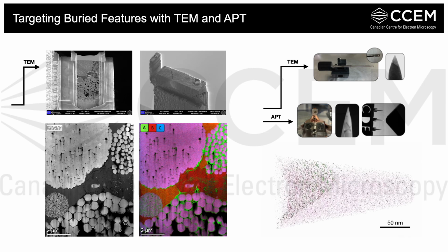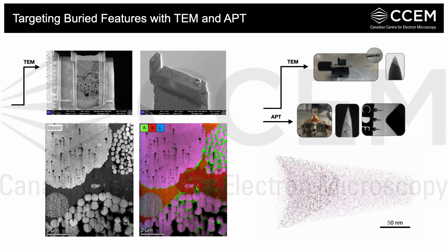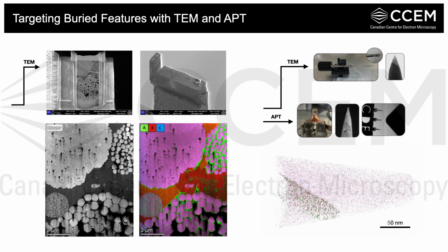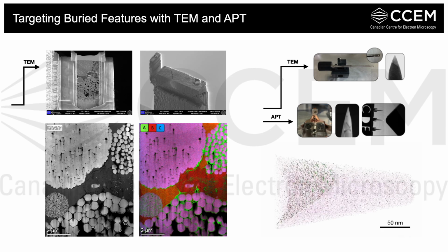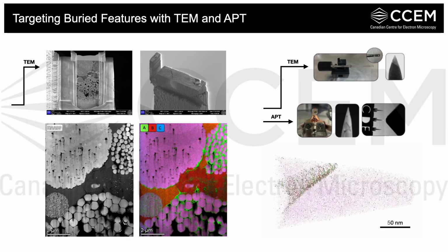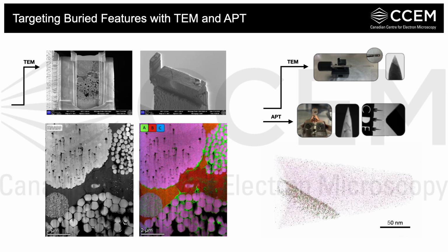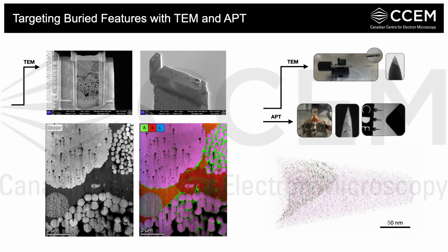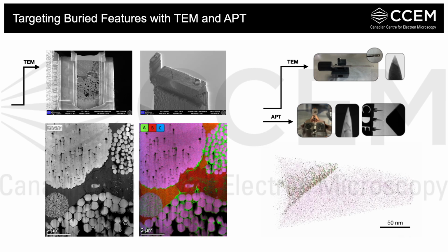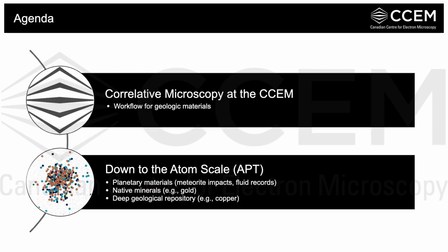So from our Atom Probe data, we can see our grain boundary, and we can see that it's decorated in a number of elements. So having context of the surrounding grains, their textures, and their chemistry, by using EDS on the micron scale and nanometer scales, this only aids in our interpretation of our final APT results. So that wraps up part one.